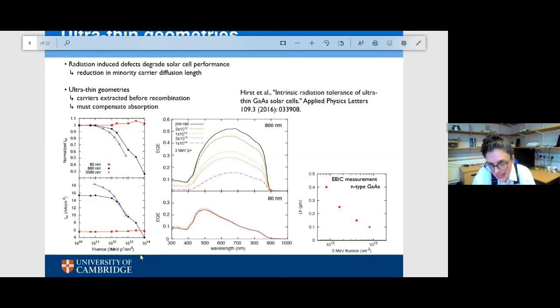If we look at the chart directly beneath, though, we can see one of the main design challenges we have with ultra-thin, which is in the 80 nanometers of material, you absorb very little light, even if you do have a good absorption coefficient. And what we really want to do is shift that line up so that we can get these good beginning of life and end of life performances. And when we look at the chart in the middle here, the external quantum efficiency, we can see how it really plummets in the case of slightly thicker devices, 800 nanometers, which is actually still very thin by modern standards. Whereas with the ultra thin 80 nanometers, we get almost no degradation in performance, but of course it's a lower performance cell to start with.